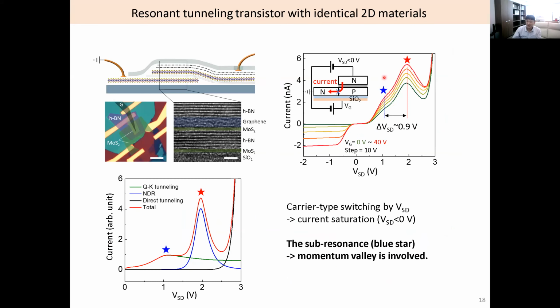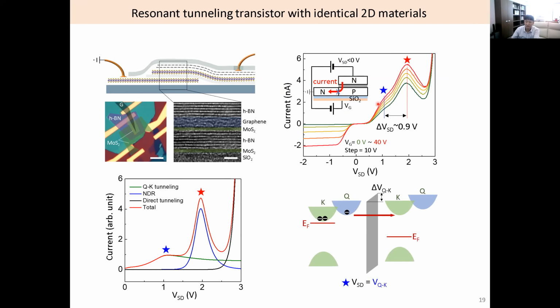So I will accelerate my talk a little bit. To confirm our mechanism, for example, if we apply this polarity of bias, here in gating, we make this N-type electron accumulation. And by this, locally here, across this parallel capacitor by hBN, we have this electron accumulation, hole accumulation locally. So we have an NPN junction. So we have this saturated current, and we confirmed our transport mechanism. Of course, this blue star can be explained by another, the second lowest conduction band, which is located at the Q point.